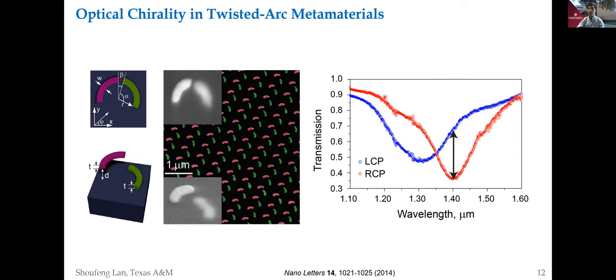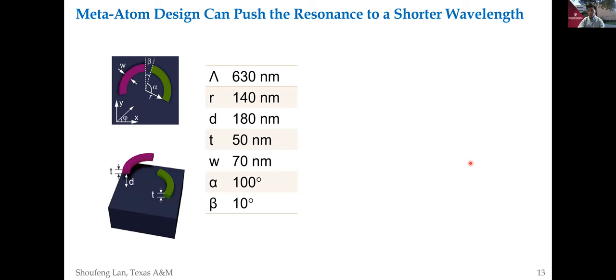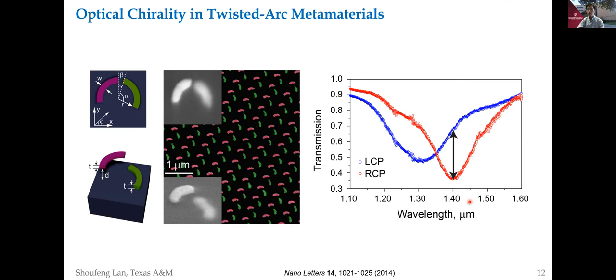You can see the figure on the right shows the transmission difference of LCP and RCP light in the infrared wavelength range from 1.1 micron to 1.6 micron. The chirality is huge. For example, at the wavelength of 1.4 micron, you can see the transmission difference will be around 0.3, which corresponds to an optical rotation of around 30 degrees.